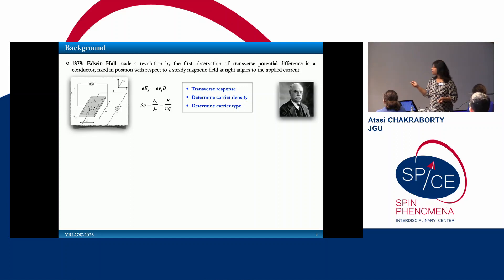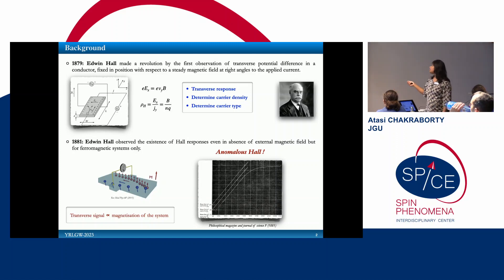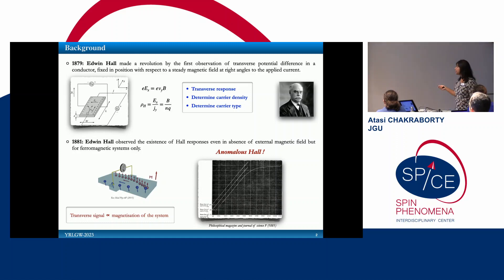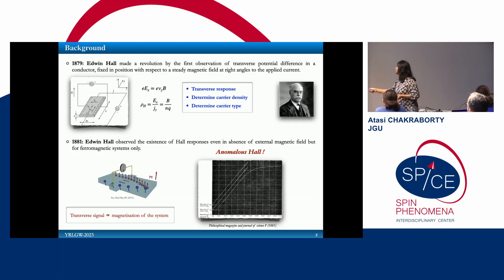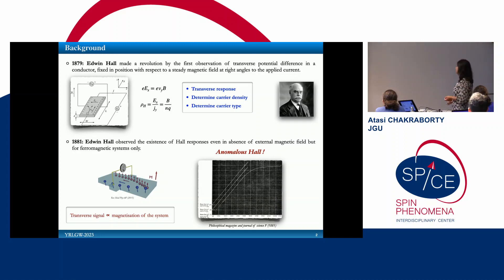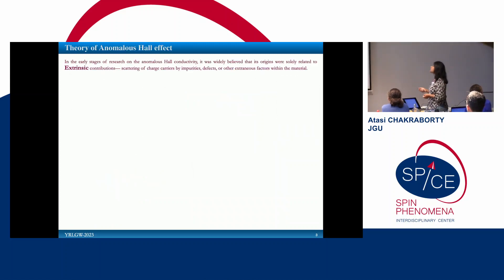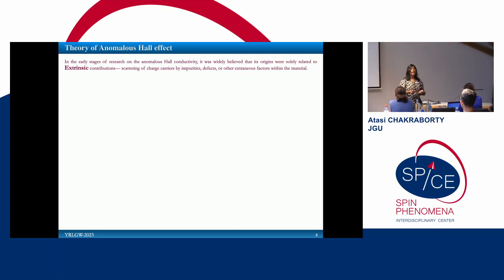One might think that turning off the external magnetic field eliminates this effect, but that's not true. Within two years it was reported that Hall responses can occur even without any external magnetic field, proportional instead to the magnetization of the system. This is observed in ferromagnetic systems. This original article plots magnetic field on the x-axis, and even when the field is zero, a finite Hall response is obtained. The origin was unknown, so it was termed the anomalous Hall effect. For a long period, its actual origin was controversial.